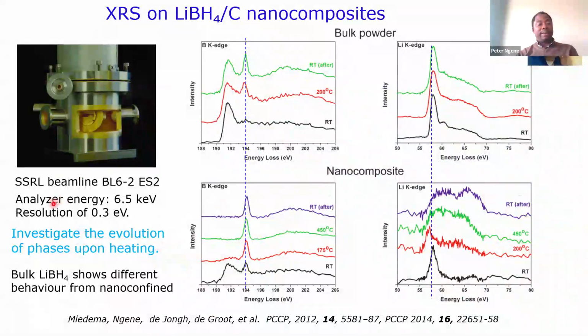So we took this sample to SSRL, beamline 6. And so basically the idea is to look at what happens when we decompose this material. So we want to investigate the evolution of phase upon heating. So we made this reactor that took some years to make, so we are able to flow gas through this, and then we can heat our sample at the same time. So it wasn't a very successful experiment, but of course there are a lot of complications when you do something the first time. So we started with our bulk material.